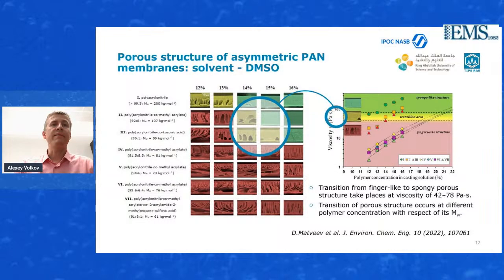And interestingly, I really like that data. When we cast the membrane based on different polymers but the same concentrations, we can achieve quite different morphology of the membranes. We can note a certain transition from the finger-like pores to the sponge-like pores here as well. And that's mostly because of the viscosity. For that particular case, we used DMSO. And we found that if the viscosity is in the range of 42 to 78 Pascal second, that's a kind of transition range where we get a mix of the finger-like and sponge-like structure. But for higher viscosity, we will always get the sponge-like structure.